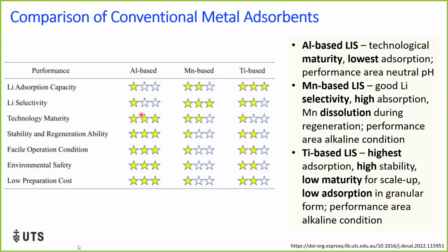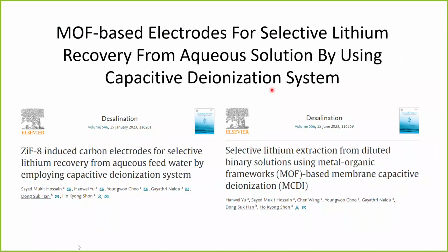Aluminum based, so you have a very strong merit for this performance. Then selectivity wise, manganese lithium oxide has a very strong selectivity, and titanium lithium absorption capacity has a very strong performance from these three metal absorbents.